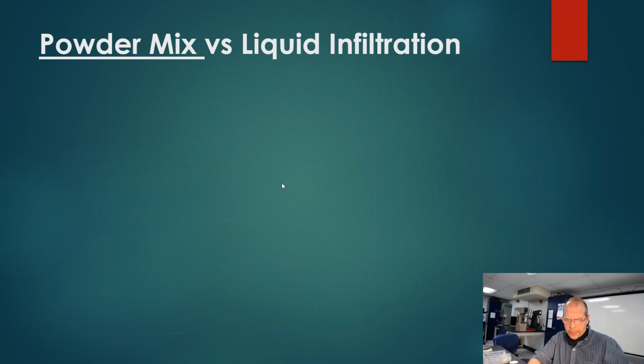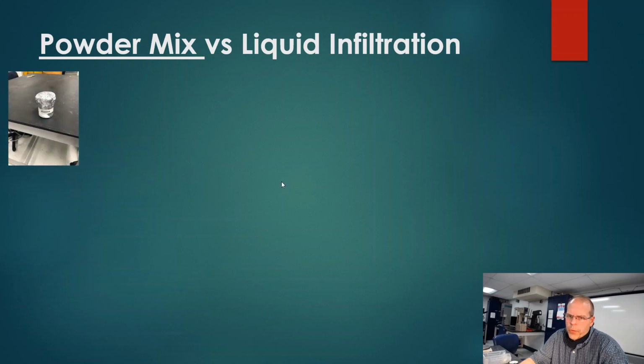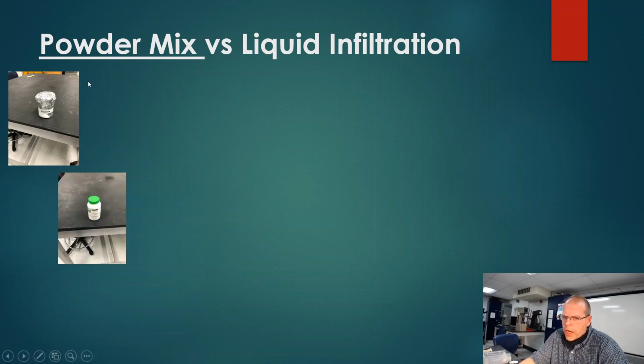Professor Sheldon in your lab has basically given you different proportions of zirconium oxide. We're going to make a series of samples, but one sample is going to have a little bit more zirconium oxide, the other a little bit less. And one of the ways we do this is we are going to make powder mixes of the two powders. So again, we're going to start with alumina.